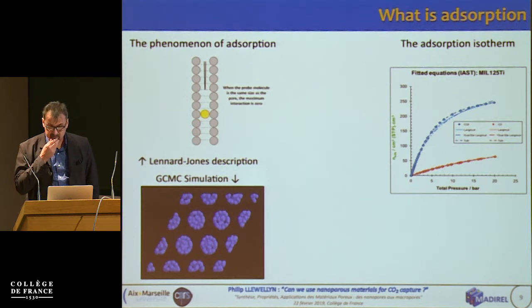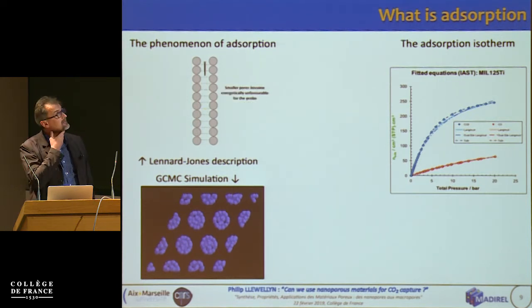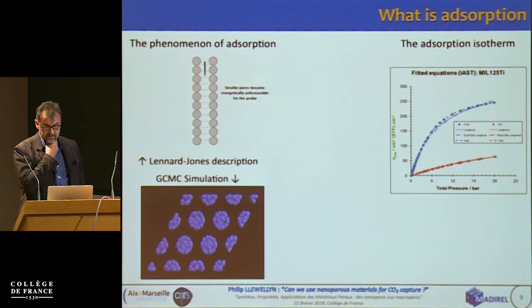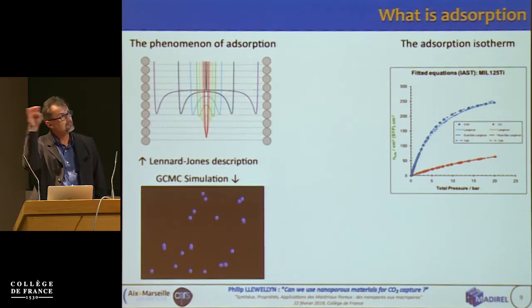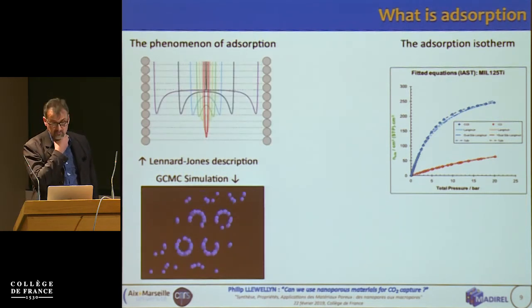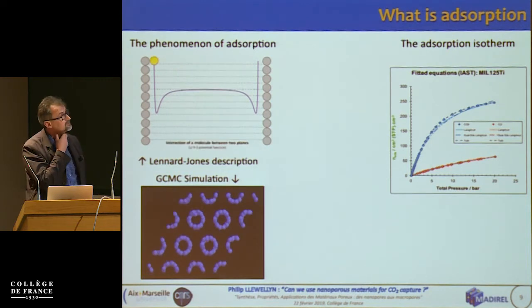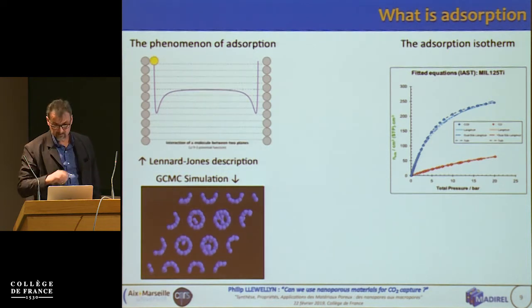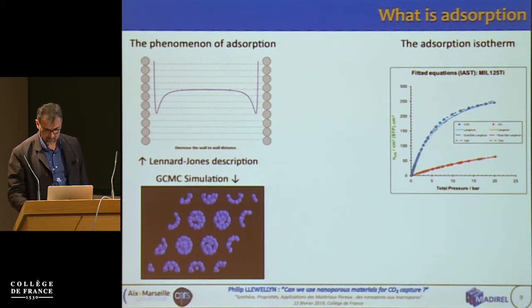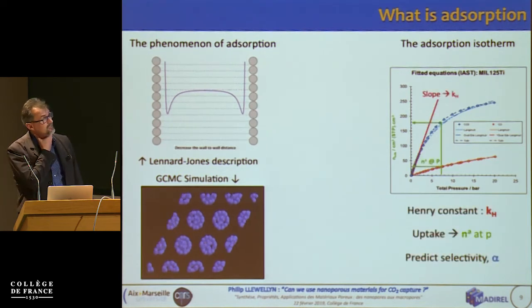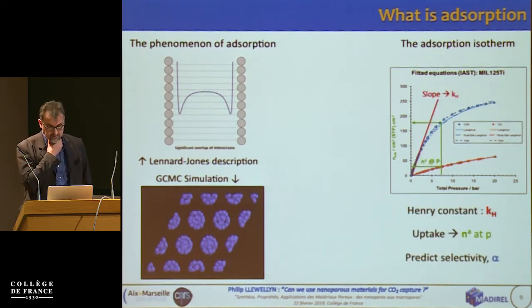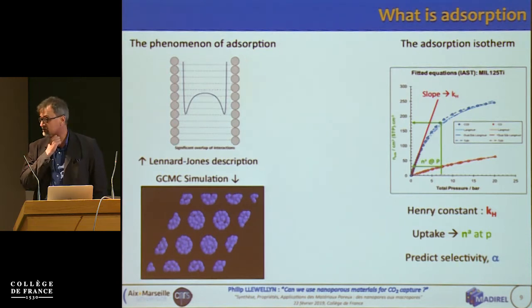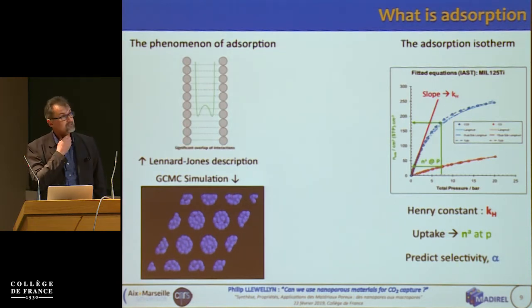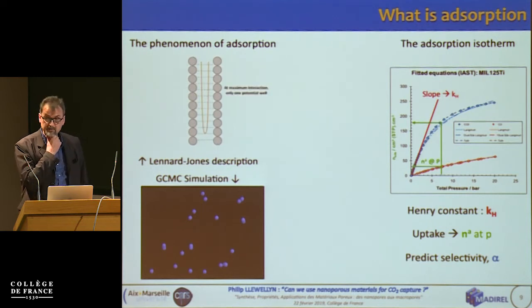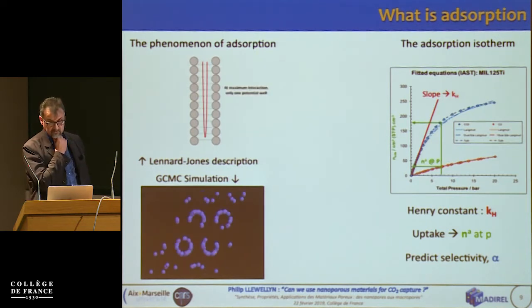The experimental points are the points. We can theoretically model the behavior of the gases, and we can do this using different models, and this is just showing you one or two here, not of interest for the moment. What we can then do is calculate the initial slope. And we already heard someone talking about the Henry constant this morning. So basically, the greater the slope, the stronger the interaction, the higher the Henry constant.